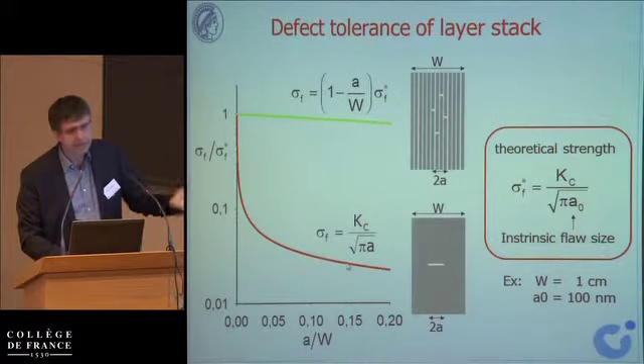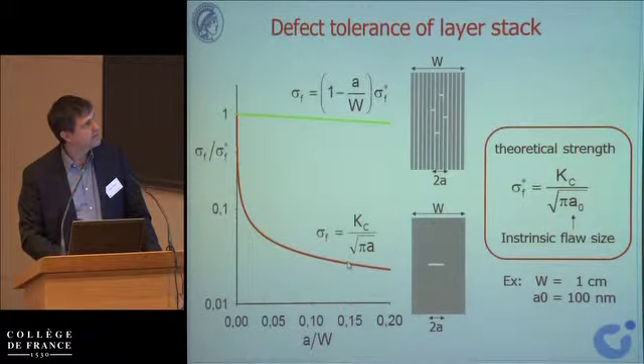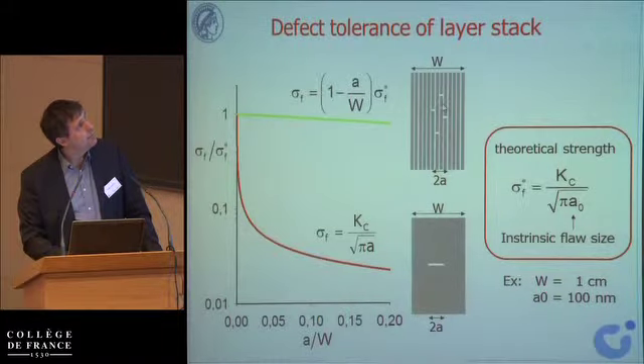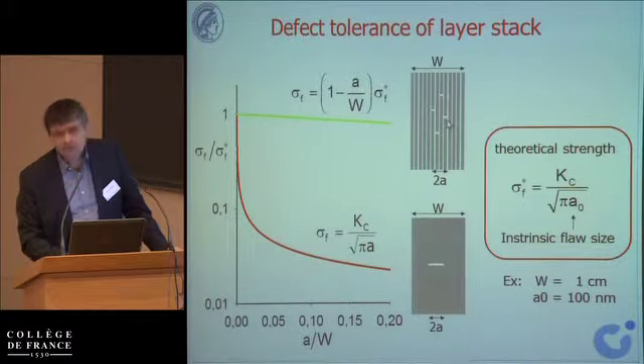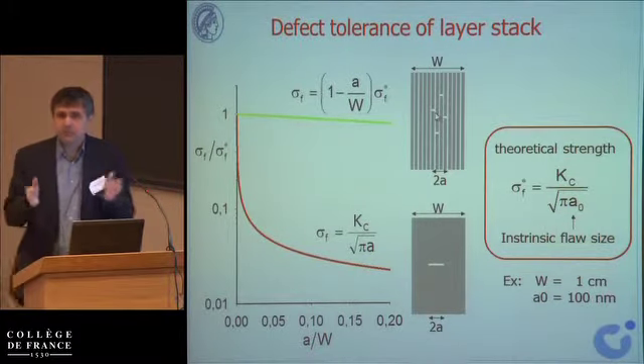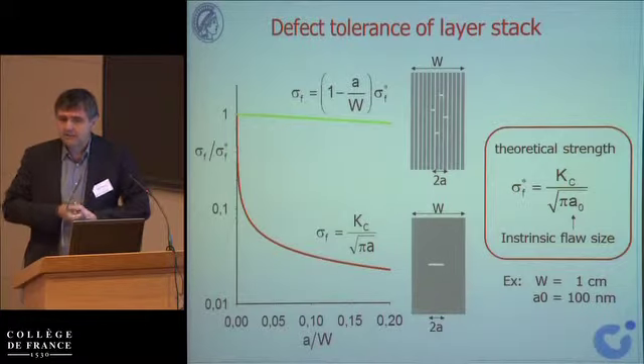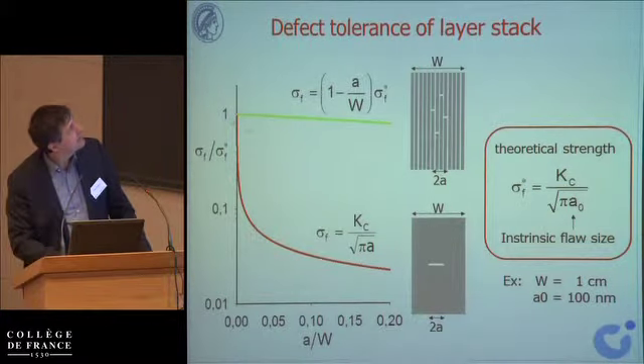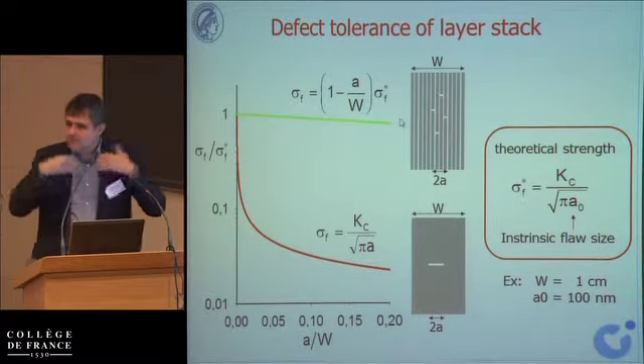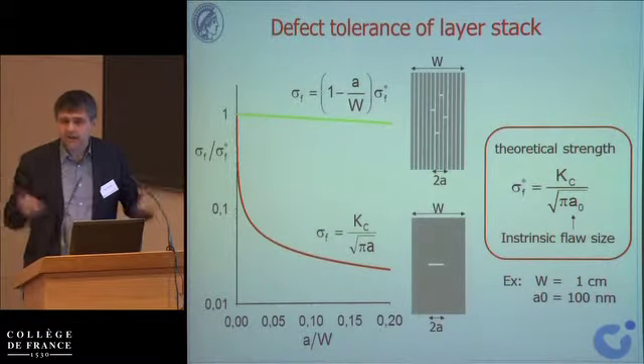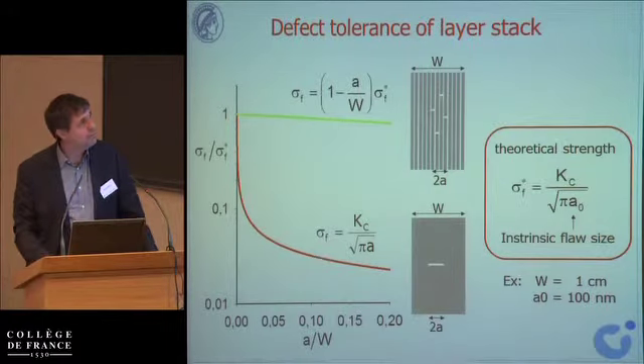That's for a completely brittle material such as a ceramic. Now take this brittle material and subdivide it into individual sheets, and I'm putting the exact same length as a crack, just that this now cracks 1, 2, 3, 4 of those sheets. The only thing you did, if this was a telephone book, is remove 4 pages of your book, and if you had 1,000 pages, now you have just 996 pages. It's still good, yeah? And the strength just decreases like this. It's a dramatic improvement in the properties just by going from a plain thing to a multi-layer thing.